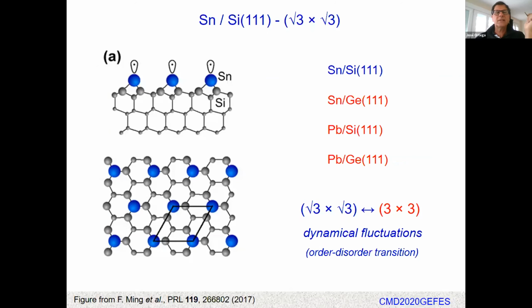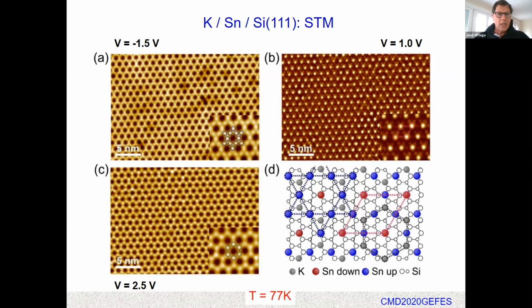So we deposit on this surface 1/6 of a monolayer of potassium atoms, and these are the STM images that you can get at a small negative bias, 1.5 volts. You can see these bright atoms, which form a Kagome lattice. You can see this in this inset, bigger image, which are these blue atoms that we call the tin up atoms. At a small positive bias, so we are seeing empty states here, we see these bright atoms forming a triangular lattice, which are these red atoms here, which are the tin down atoms. And if you go to larger positive bias, what you observe in STM is this honeycomb lattice, which corresponds to the potassium atoms.